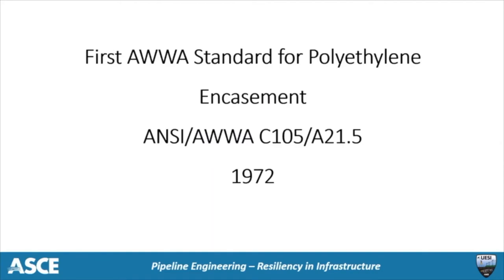In today's standard, the polyethylene is required to be a minimum of 8 mils thick rather than the 7.2 mils shown for the 1972 standard. The current standard also calls for linear low-density polyethylene, which is significantly stronger than the low-density film found in the first several revisions of the standard and the film used to encase the Lafourche Parish pipe in 1958.